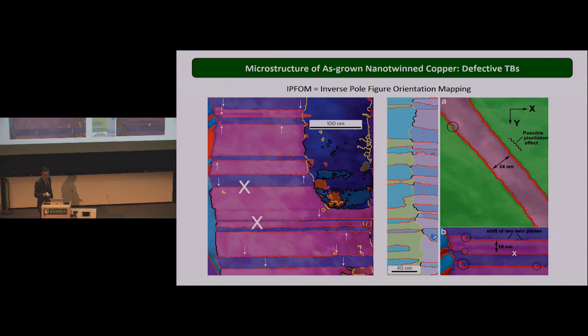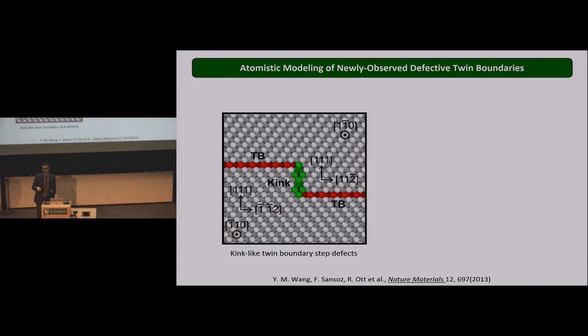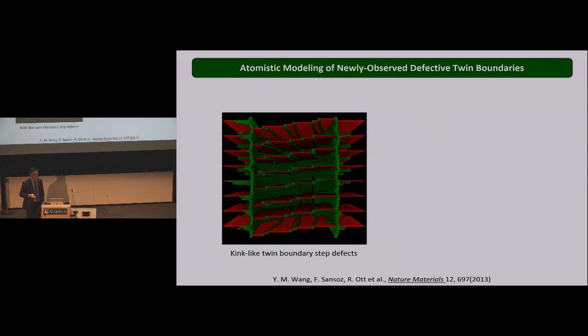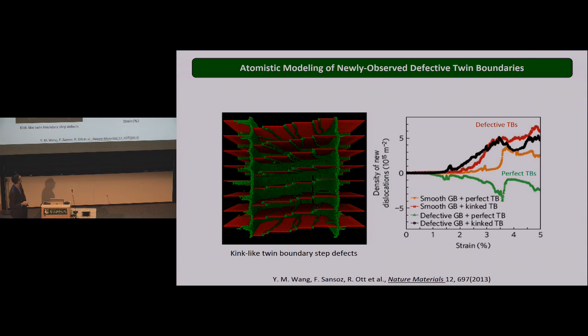Okay? And so this information was extremely important for me because I could redesign my atomistic simulation to include those defects. This is an example where we have the twin boundary here, and we included one of those step defects, and we call them kink steps because they look like kinks. Then we made a larger model with a lot of them, and we just repeated the same simulation. And the results are totally different now when we have the presence of the defect.